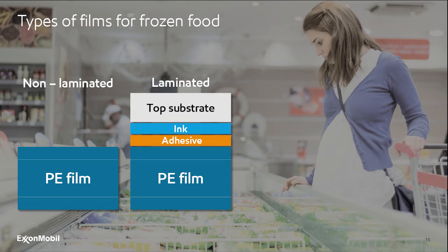So you still have a polyethylene film to start with. This film, the laminated film, is made in a 2-step process. So you have the polyethylene film, which you glue together by an adhesive with the top substrate. The top substrate is typically made out of other material than polyethylene. It can be polypropylene, it could be PET, and in some cases can be polyamide.